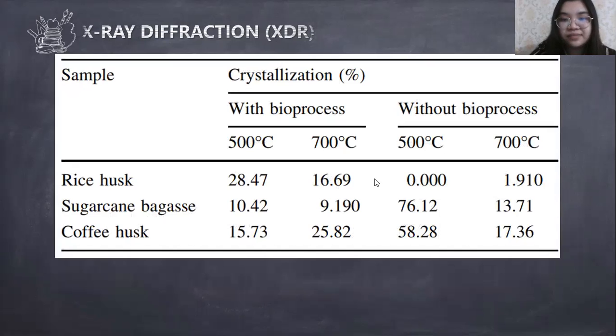Okay, the last result. This table shows the crystallization percent that was obtained both via bioprocess and without it. We observed that for rice husk, it is not enough to transform it into amorphous phase. However, the annelids' metabolic effect increased the crystalline phase as it was 28.47% for 500 degrees Celsius and 16.69% for 700 degrees Celsius. For sugarcane bagasse, it is the opposite from the rice husk. The crystalline phase is lower with bioprocess and higher without bioprocess.